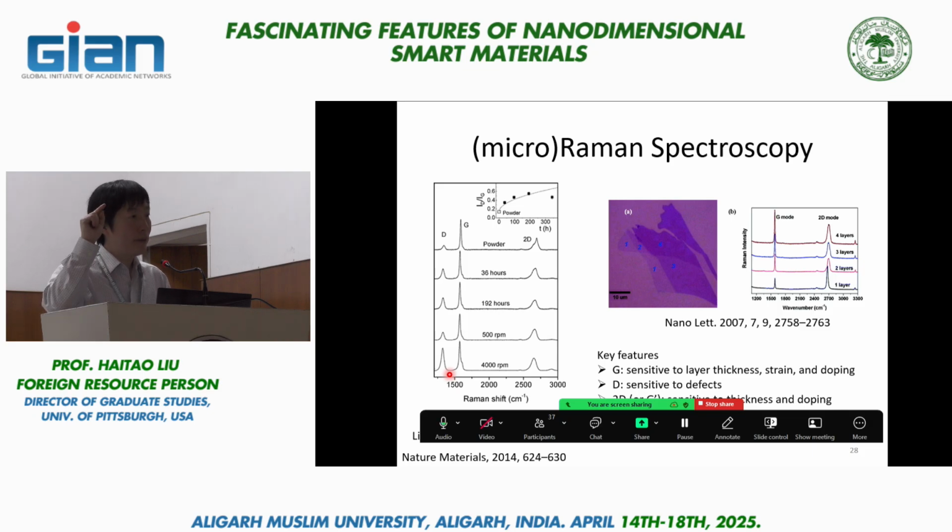Now, if you think about the bulk, as I said, it's different from molecular species. In a molecular benzene ring, you have this ring breathing mode. But in bulk graphene, you cannot have that breathing mode if there's no defect, because you cannot have all the rings breathe at the same time. It just doesn't work that way, because it's an infinite chain of rings.